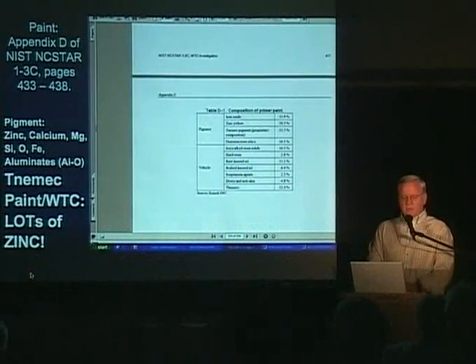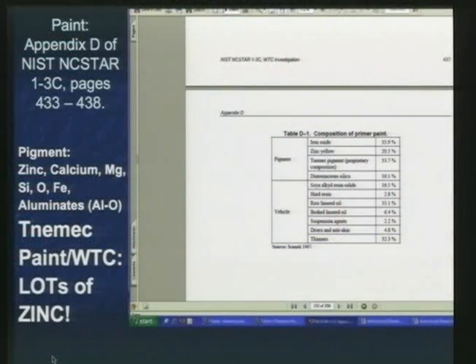Now here's the primer paint used by Tnemec, supplied by Tnemec for the World Trade Center. We see that in the pigment, this is from Appendix D of the NIST report. We get facts from NIST, and they simply report the pigment and the components in the primer paint, which is high in zinc, magnesium, aluminates, calcium, and so on.